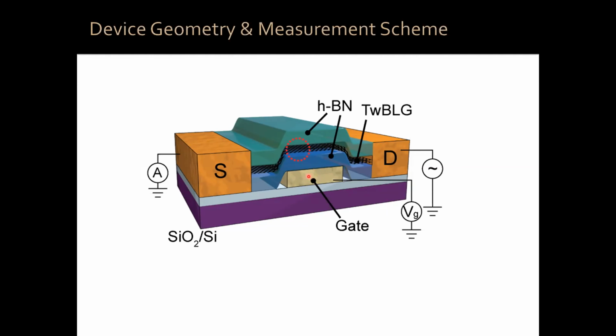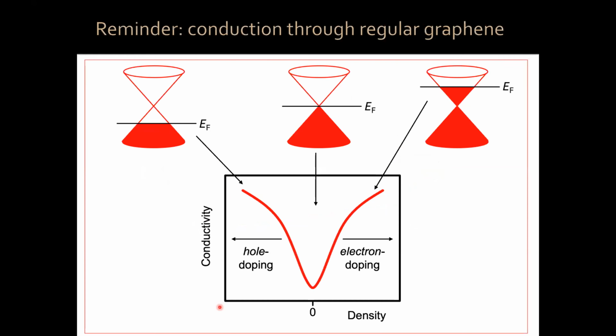Okay, so just as a reminder, what happens if you only had one layer of graphene, not twisted bilayer graphene, but just one layer of graphene? If you measure the conductivity versus density for one layer of graphene, you have this V-shaped behavior. If your Fermi level is deep into the valence band, you have lots of holes, so you conduct very well. If your Fermi level is deep into the conduction band, you have lots of electrons, so you conduct electricity very well. If your Fermi energy is at charge neutrality or at the Dirac point, you have very few charge carriers, so you conduct poorly. So the conductivity of regular graphene versus charge density or gate voltage is this V shape, okay? And this has been seen by thousands and thousands of groups now.